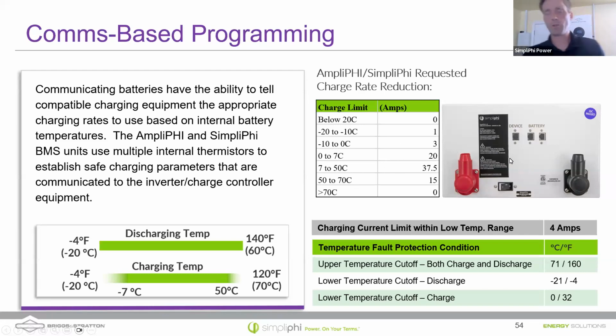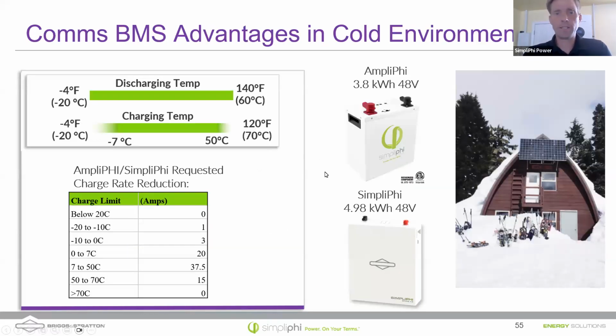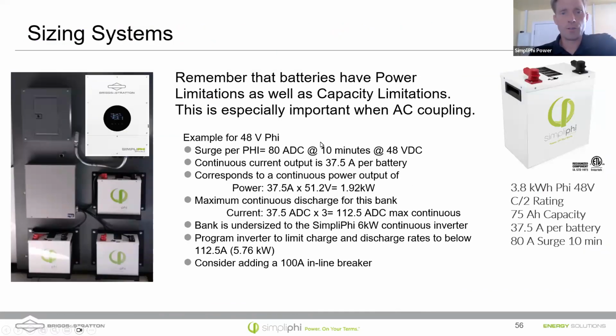So there's a lot of features to the more advanced BMS units in the SimpliPhi and AmpliPHI battery that you can take advantage of if you have temperature considerations to pay attention to. If we go above a 4 amp range when we're in low temperature conditions, so 0 to -20, the battery will protect itself by opening up the contactor. If we try to charge above 71°C, it'll cut off both on charge and discharge. And then there's a cutoff for discharge at low temperature. If we're above 4 amps at -21, it'll cut off, and similar for the charge cycle. So these are the cold weather solutions that I was mentioning to you for these communicating batteries. So if that's of interest to you, let us know.